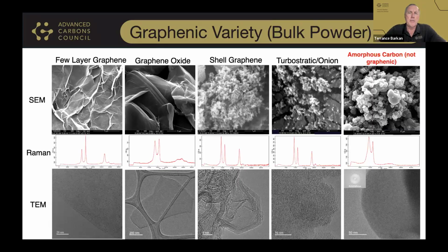And there are many different ways of making graphene, not just from graphite as a feedstock, but increasingly graphene is being made, for example, by folks that are producing hydrogen from a gas, taking methane, or you can take oxygen and acetylene and create graphene out of that. So using gas precursors results in a form of turbostratic or disordered flakes of graphene. And then lastly, you also have amorphous carbon, which is not graphene, but depending on the optical spectroscopy or microscopy, it might look like a graphene material, but it's important to distinguish the differences. And then in the TEM images below, you can see the difference in particular, where we can get right down to the level where you can actually count the individual carbon layers.